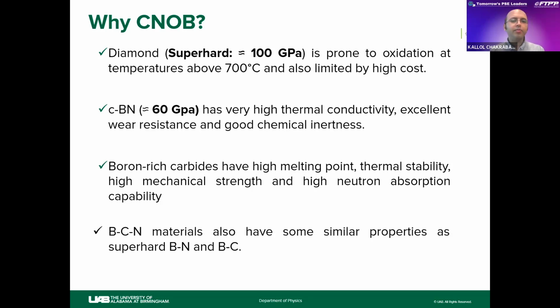Our second hardest superhard material is cubic boron nitride, but its hardness is around 60 GPa, and it has high thermal conductivity, excellent wear resistance, and good chemical inertness. Boron-rich boron carbide, another material from the CNOB system, has high melting point, high thermal stability, high mechanical strength, and high neutron absorption capability. The ternary BCN material also has similar properties to superhard boron nitride and boron carbide.